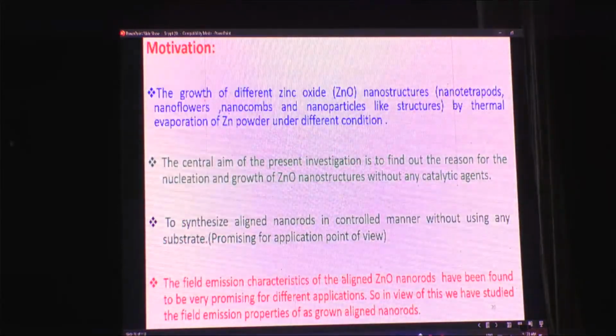With its help, we found various wonderful structures by controlling the flow of argon, oxygen, and the amount of zinc. The melting point of zinc is very low, nearly 400 degrees centigrade. So the motivation of this work is different.